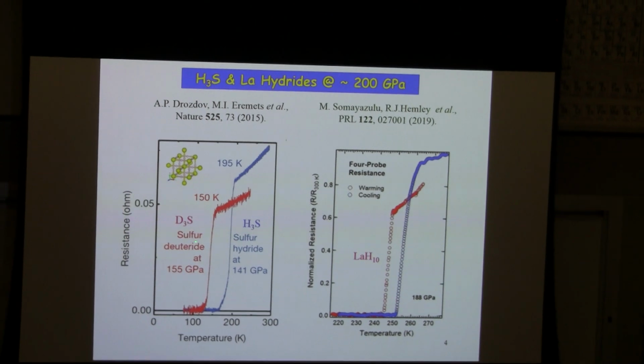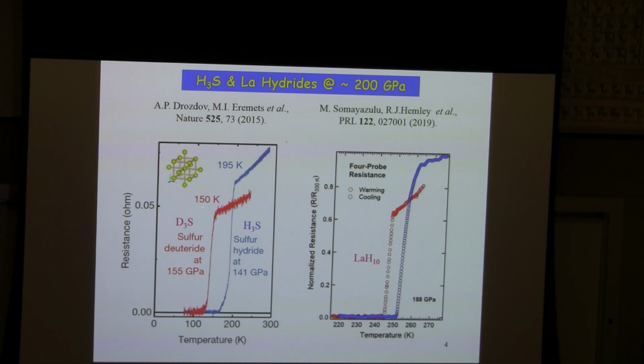This is the element data. The chemical composition and structure are known for H3S, which shows a TC of almost 200 K under a pressure of 150 GPa. And quite recently, lanthanum hydride, although the structure is not known yet, when near 200 GPa pressure was applied, these authors reported that TC is almost 260 K.